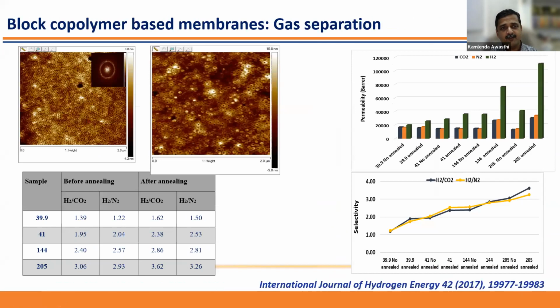So what we could do, again, we tried different molecular weights, and like before, having a perfect arrangement before annealing and after annealing, and then we again measured the gas permeability for different molecular weights. And here you can see the molecular weight denoted by 205 and anneal, they have the higher permeability in comparison to the molecular weight that is 39.9.